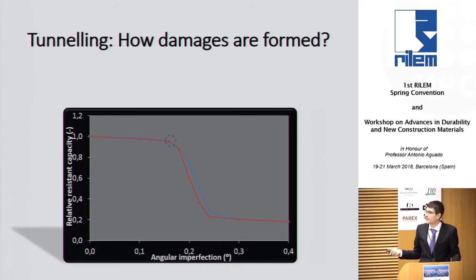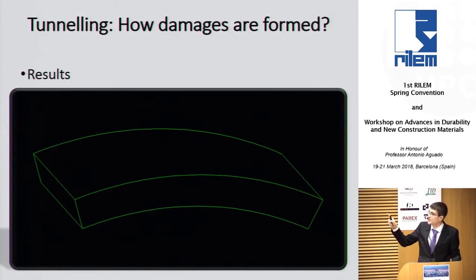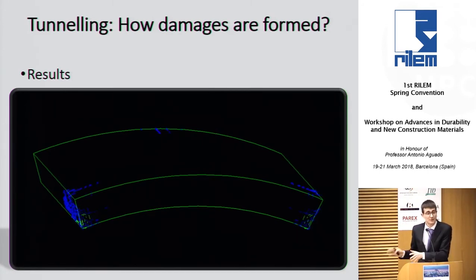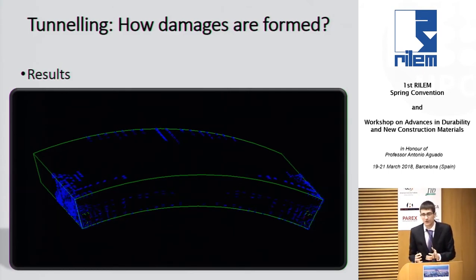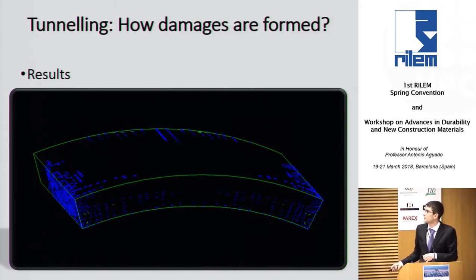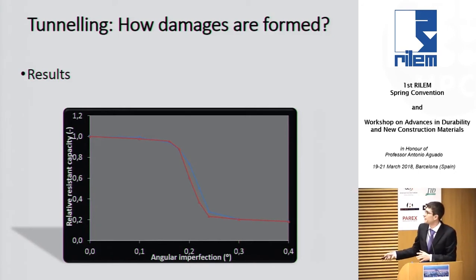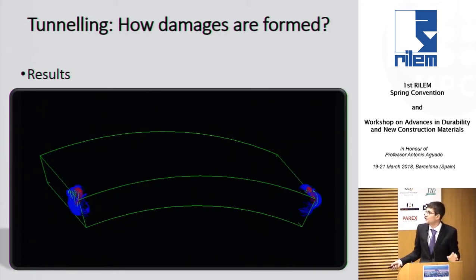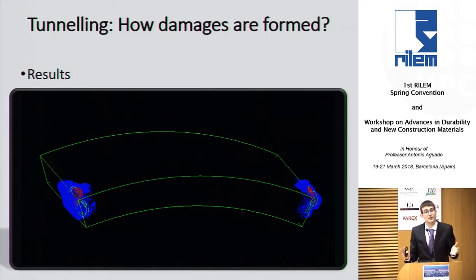And for instance, in a point in the top part of the curve, what we would see is the result of the model with the cracking appearing. So in this case, we see cracking being formed. So this is the cracking of the segment. But the interesting thing is that for small imperfections, the cracking distributes over the segment without causing critical damage. Right, so this is what happened for very small imperfections. Conversely, for very big imperfections, for instance, this point in the bottom part of the curve here, what we had was a very localized cracking, which for small loading reached a critical situation.